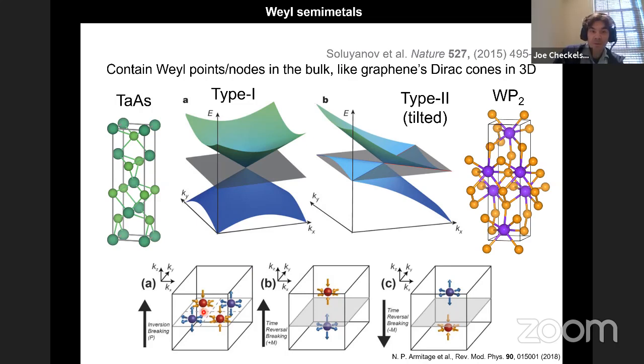There are types which are not only driven by this inversion breaking, but, to couple back to the theme of my talk, also types which are driven by time reversal symmetry breaking. And I think the appeal of these magnetic analogs, which are driven by time reversal breaking, is that the position in momentum space of these magnetic Weyl points is dictated by the nature of the time reversal breaking. So just in the same way that in the magnetic topological insulator you could change the chirality of the mode by reversing the magnetism, here you could change a very rich magnetic structure also by changing the magnetism.